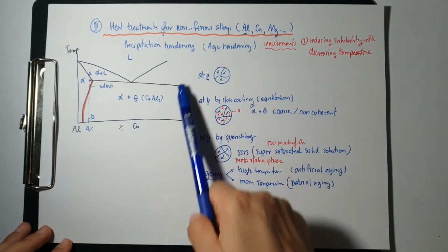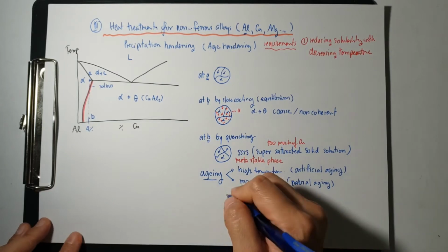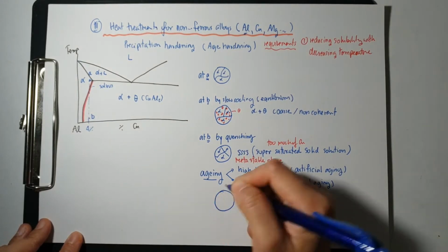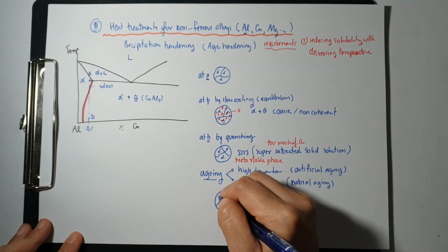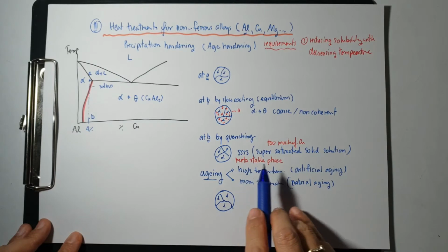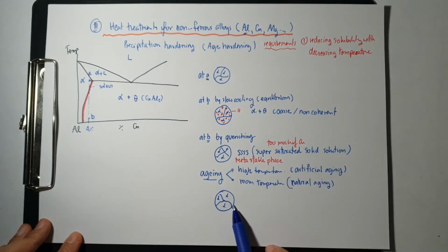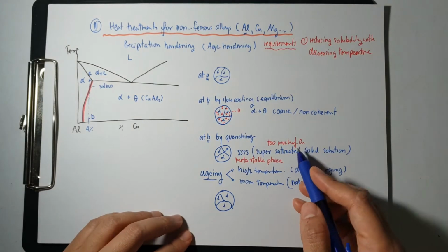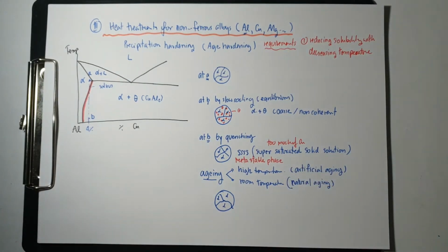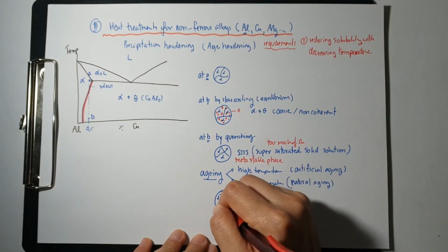If I explain the microstructure changes when we enter the aging condition, previously we have the alpha phase that has too much copper dissolved into its structure. By aging, increasing time will allow the copper to form the precipitate phase, and the precipitate phase is now very fine.